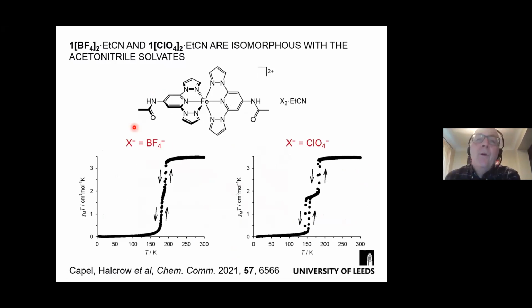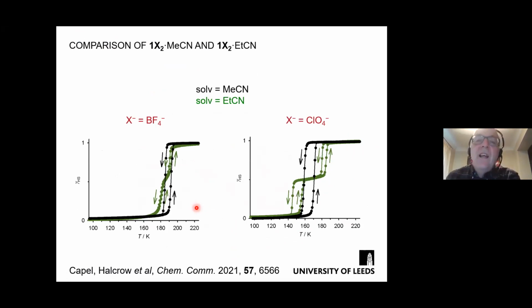Now, you crystallize from propionitrile. You also make the same crystal phase, but now we have a step in our spin transition. It's not much of a step for the BF4 salt, but for the perchlorate salt is very clear. And the comparison is very nice if we plot the acetonitrile and the propionitrile materials on the same graph.